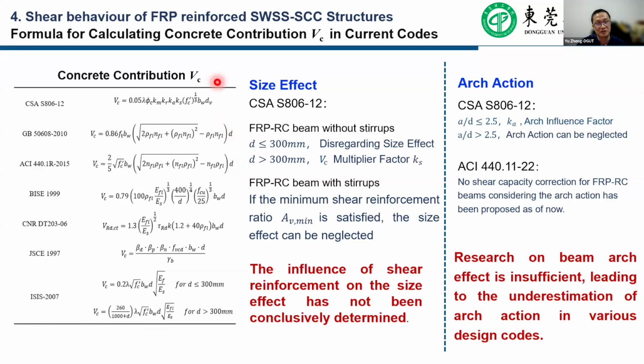But at the first stage of this study, we try to modify the prediction method for the contribution from the concrete. We also use the current design methods. We can find that the size effect and the arch effect have been considered in several codes, including the CSA model and the ACI codes. But for the CSA model, the influence of the shear reinforcement on the size effect has not been conclusively determined. And furthermore, the research on the arch effect in beams is insufficient, leading to some high underestimation of the arch action in the various design codes.